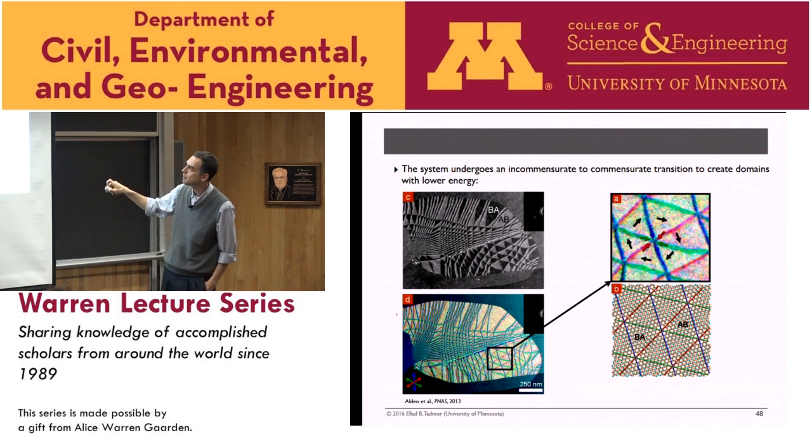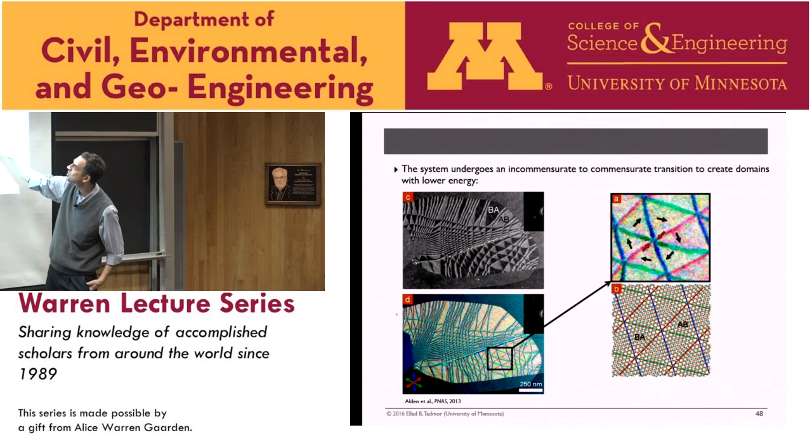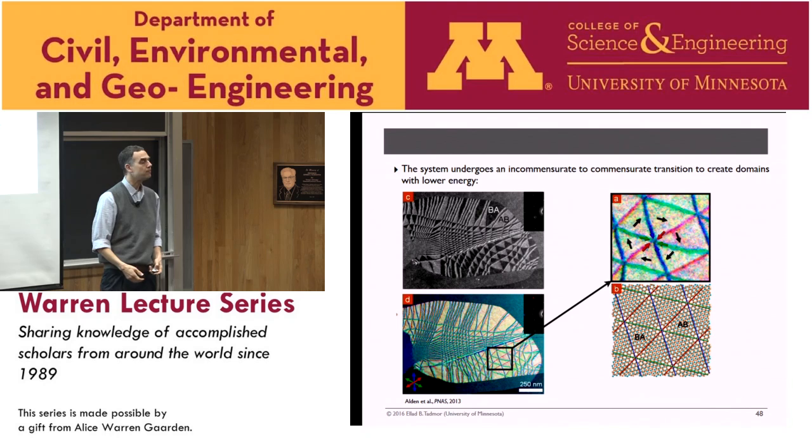And this is the same picture, just where they highlight the interfaces. When you zoom in, you get these types of regions where, in each of these triangles, if you look carefully, you have a middle region here, which is a high energy AA type of configuration, which is this state here. This is AA, where they're perfectly lined up. And it prefers to be in a BA or AB state where they shift relative to each other. That's a low energy state. And so they do everything they can to maximize the regions where they're in the low energy state. So they become commensurate and low energy.